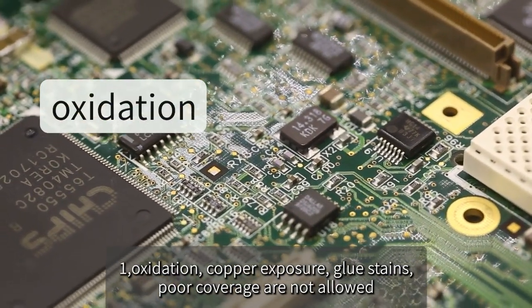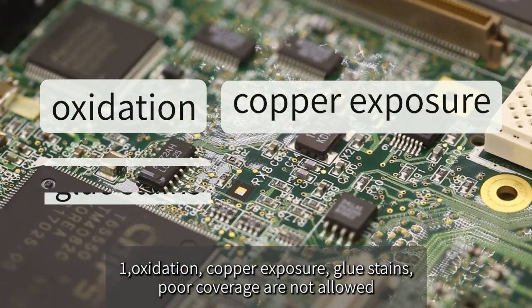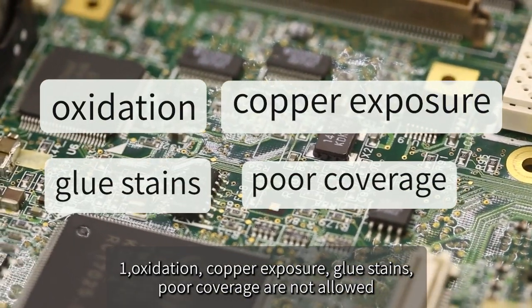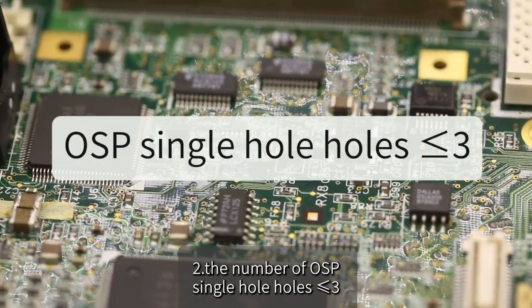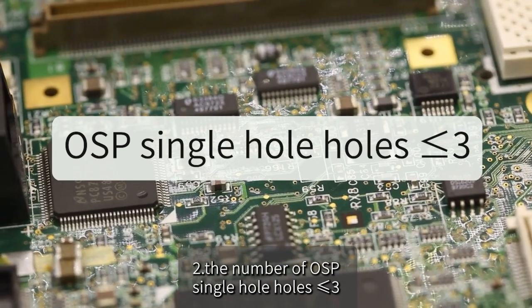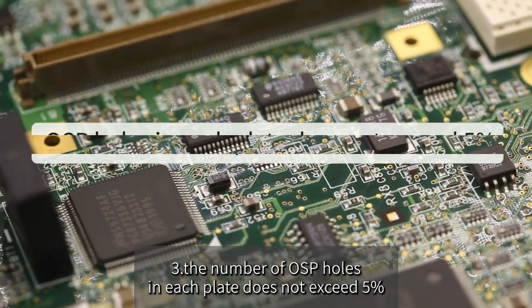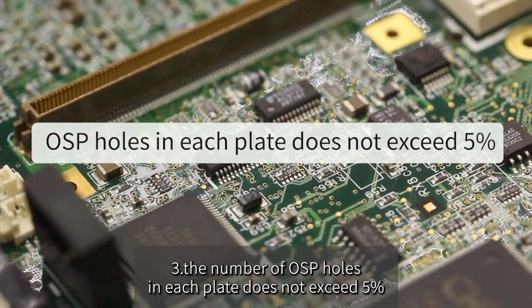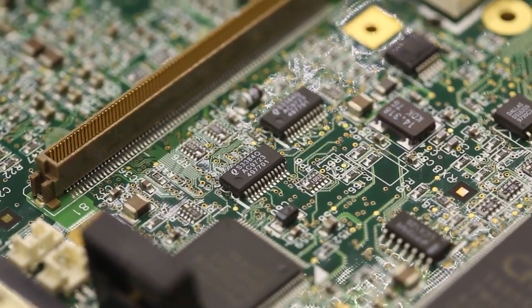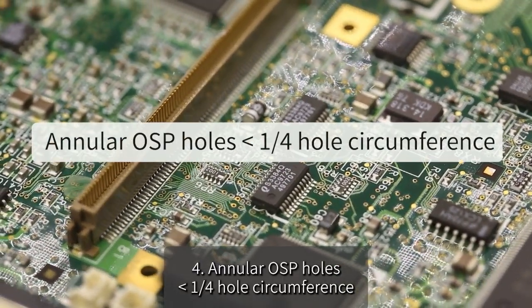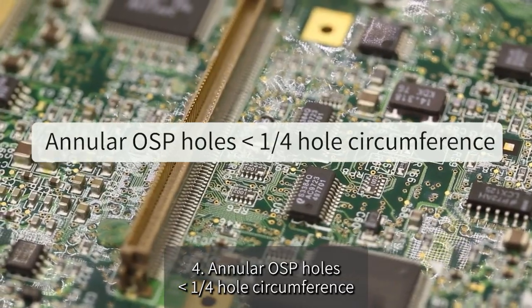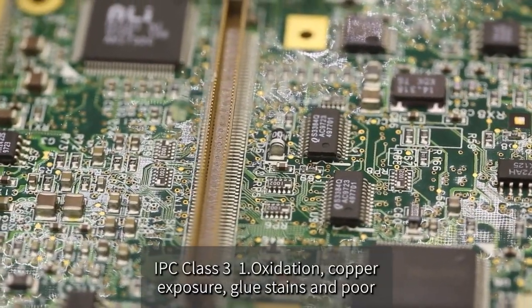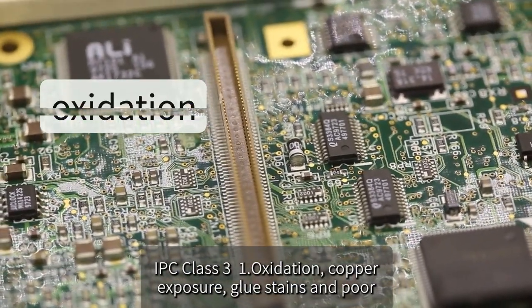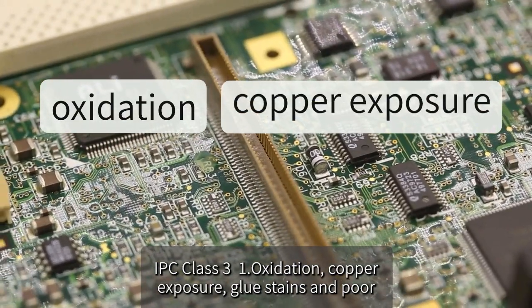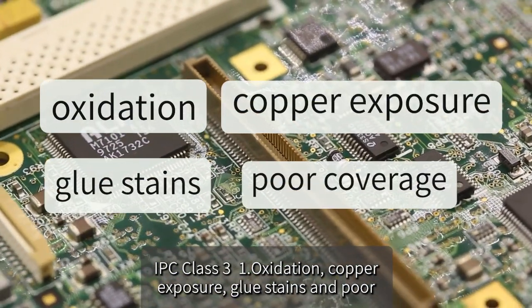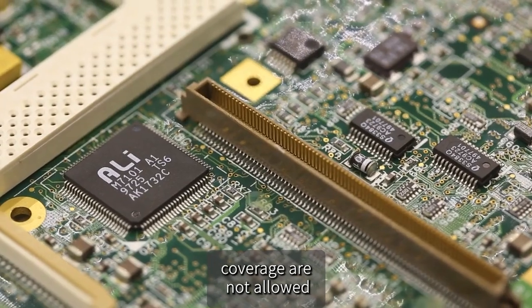1. Oxidation, copper exposure, glue stains, poor coverage are not allowed. 2. The number of OSP single-hole defects less than or equal to 3. 3. The number of OSP holes in each plate does not exceed 5%. 4. Annular OSP holes less than 1/4 hole circumference. IPC Class 3. 1. Oxidation, copper exposure, glue stains, and poor hole coverage are not allowed.